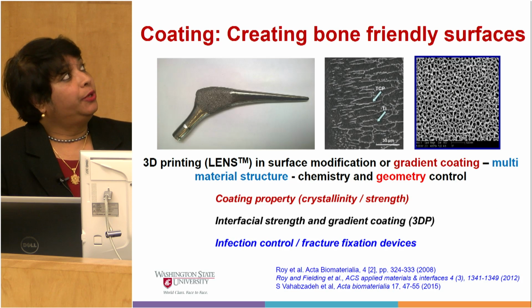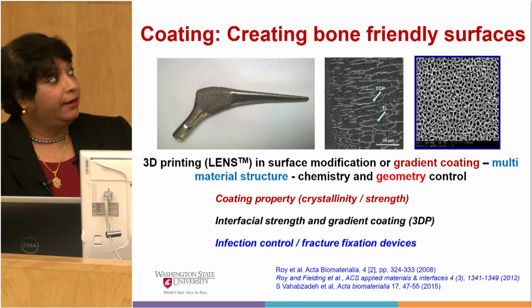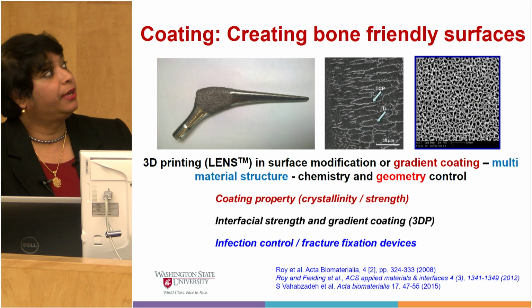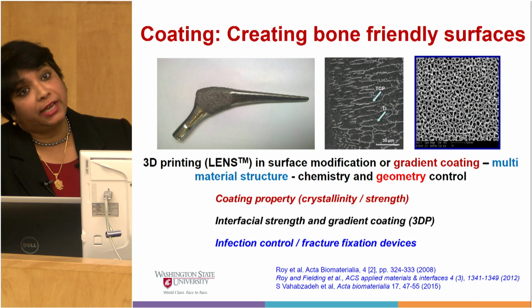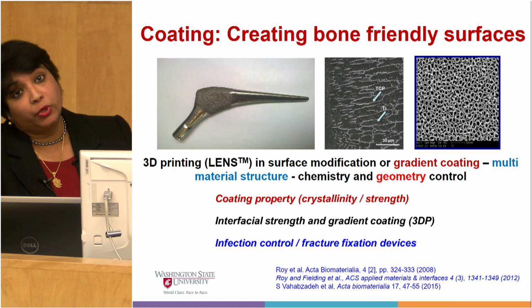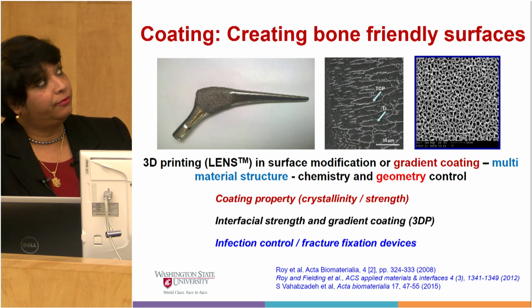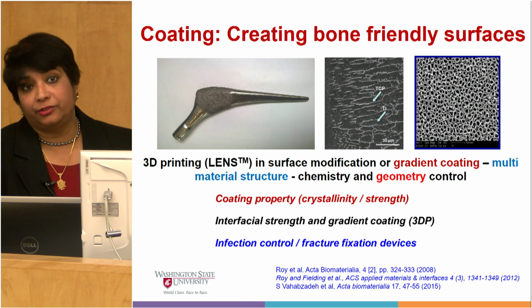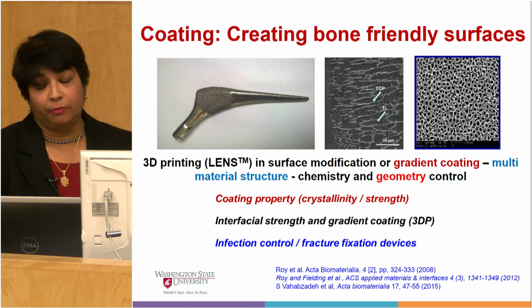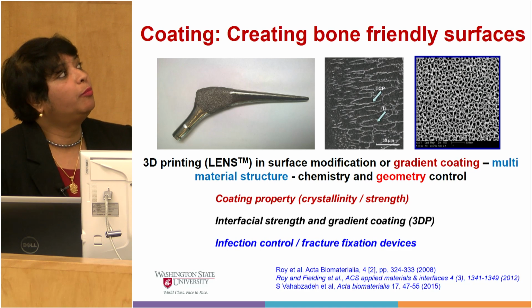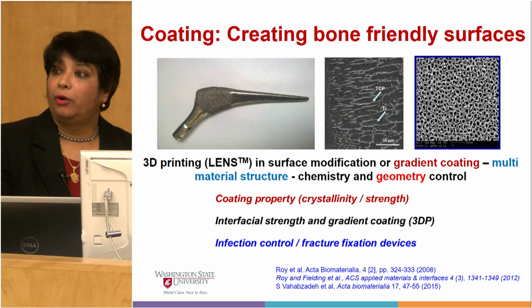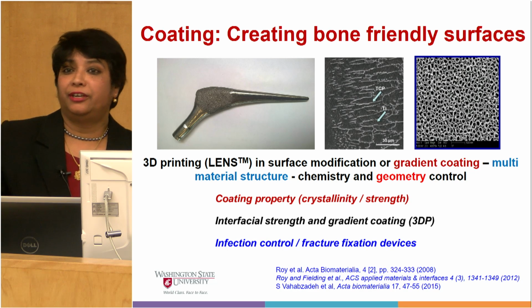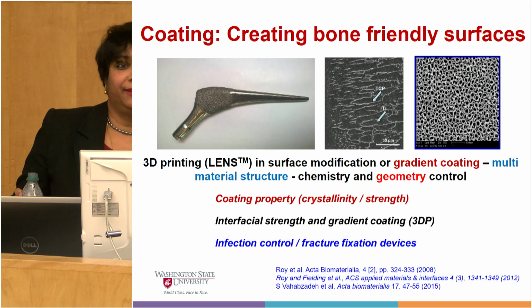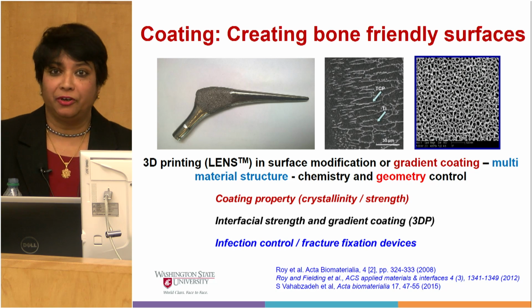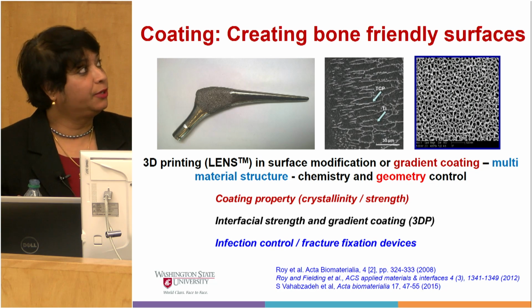We have also shown that, in terms of the surface chemistry modification, we can use calcium phosphate to coat metal implant surface and do nanoscale surface modification of the metal implant to make it more body friendly. Right now I have in the audience Ashley, Dishari, I don't see Sam here. So they all are working on this calcium phosphate coated implant.